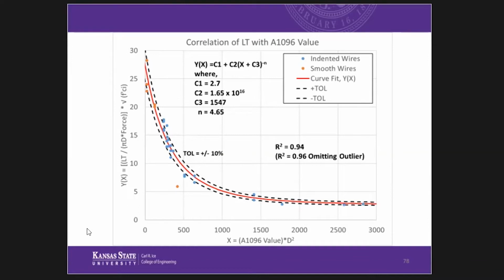So on the left axis, we have the transfer length divided by the circumference times the force on the wire times square root f'c. And on the right axis, we have our ASTM A1096 value normalized by multiplying times diameter squared. And there's one outlier here, and this is one of the smooth wires. So smooth wires in a pullout test, as soon as we start to get slip, the value drops off. So I'm not too concerned about that because nobody's using smooth wires.